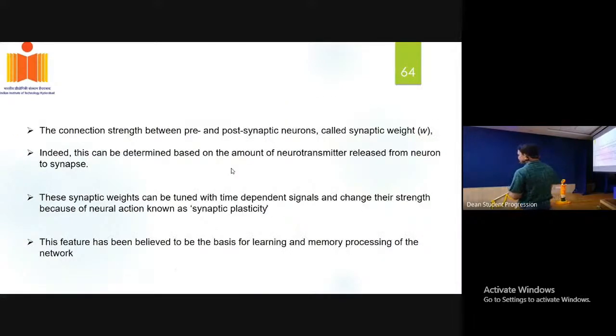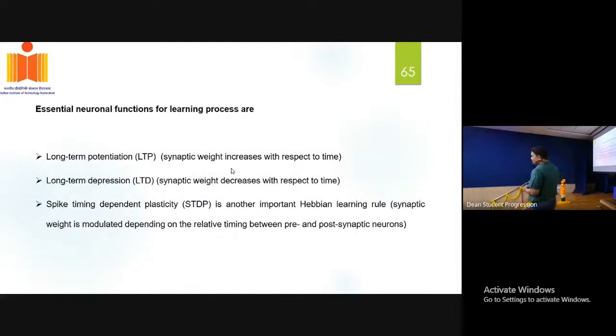Okay, so the connection strength between the presynaptic neuron and the postsynaptic neuron can be called the synaptic weight. And if you can tune this weight change by the application of different voltage pulses, if you can prove long-term potentiation, that means that the synaptic weight must increase with repeated voltage pulses. And if you can prove long-term depression by the application of voltage pulses, that means the conductance decreases, and also spike-timing-dependent plasticity. If you can prove these three important characteristics, you can say that your device is mimicking the brain functionality. Okay, so particularly long-term potentiation, long-term depression, and spike-timing-dependent plasticity.